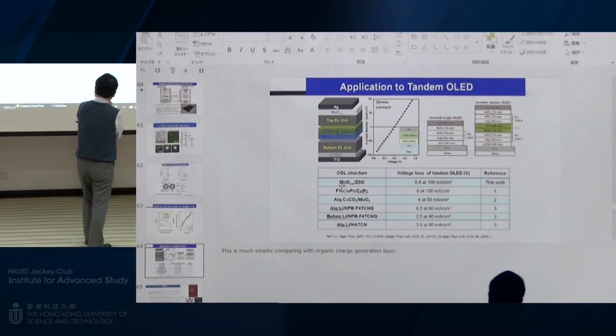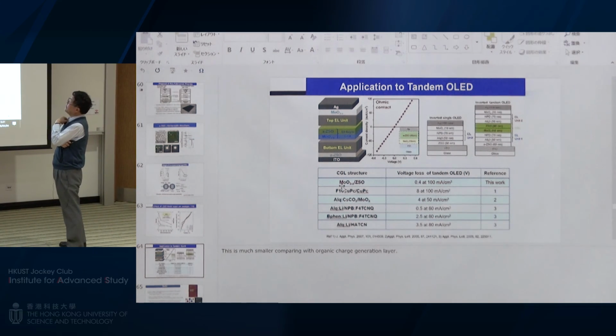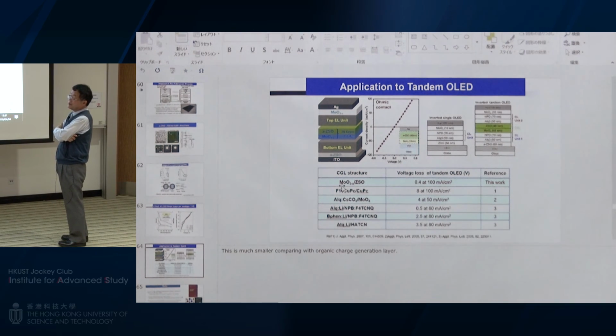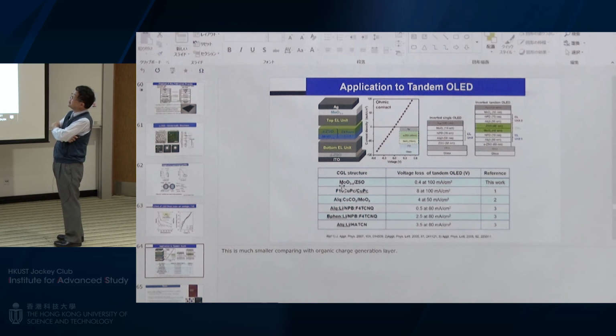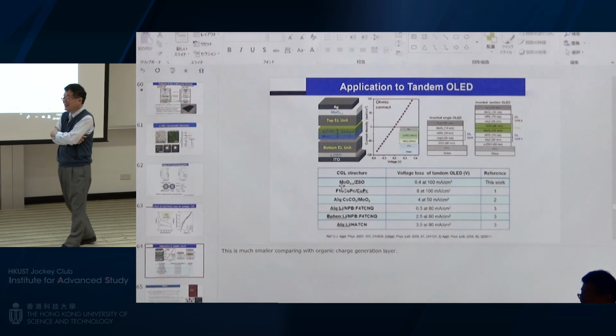Okay, so the electron concentration of the amorphous C12A7 and ZSO, the carrier concentration at the Fermi level, is very low, 10 to the 14 to 10 to the 16. No problem. Maybe it's no problem. Yeah. And also in this particular case, your ZSO has to be sputtered directly on top of the organic stack. So we talk about this also. That could be a problem as well.